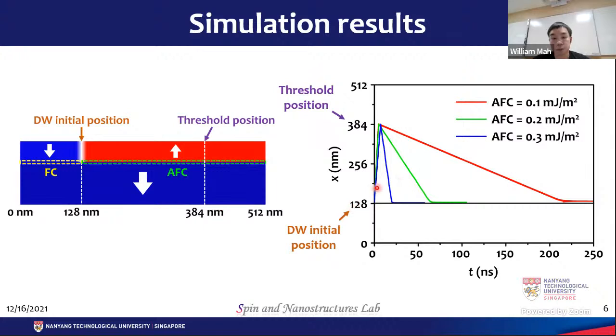I start from the initial position, I apply current. The domain wall is pushed towards the threshold position, 384. That is the integrate function. Once I switch off the current, the domain wall would automatically come back towards the initial position. That is the leakage function. The stronger my antiferromagnetic coupling between the top and the bottom layers, the faster it comes back down.